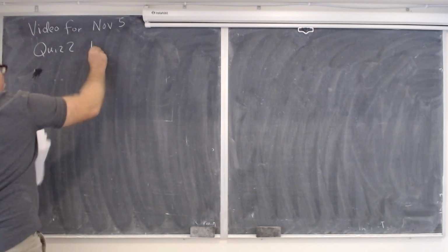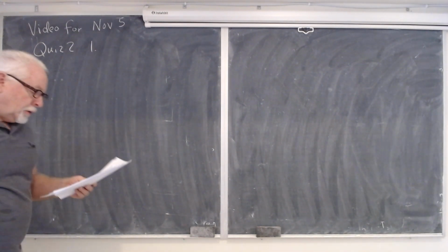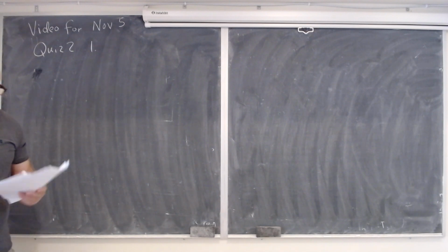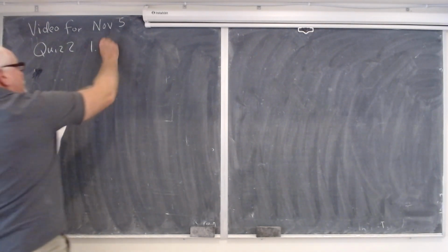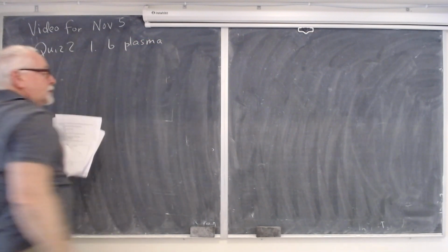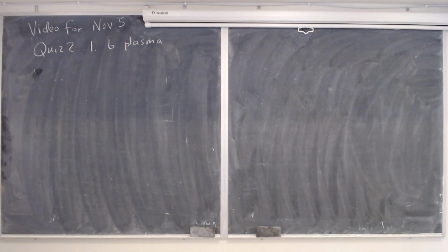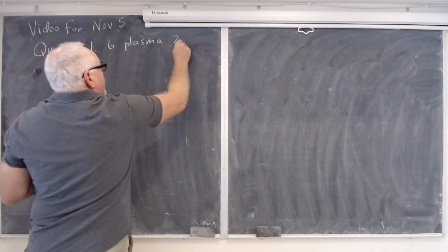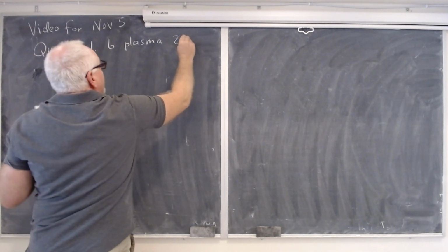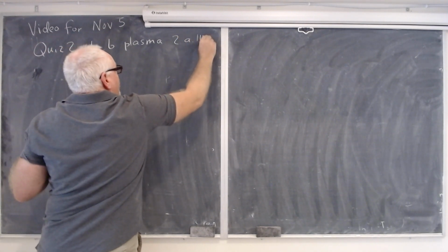And problem 1 was just a qualitative problem that I expected you, from the review and everything else, to know the answer of. For patterned etching of silicon nitride, you would want to use a plasma, B, because you get much less undercut and much more control over the etch. And number 2, you should know by now that KOH etching stops on the 111 plane.